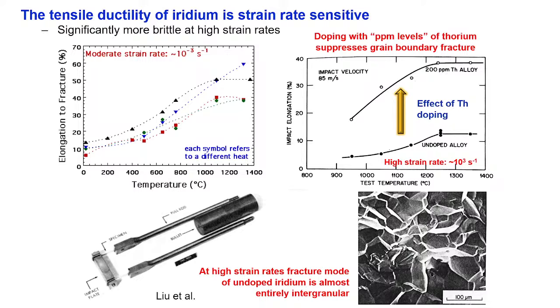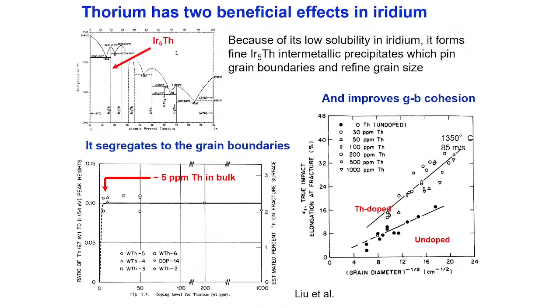And we understand now the mechanism, how thorium improves the ductility. It does two things. Actually, it does three things. The first thing is that we look at the iridium-thorium phase diagram. The solubility of thorium in iridium is almost zero, so the tiniest amount of thorium comes out as iridium-5 thorium intermetallic precipitates. These precipitates then refine the grain size because they pin the grain boundaries and prevent the grain size from getting too large, and that's one way.